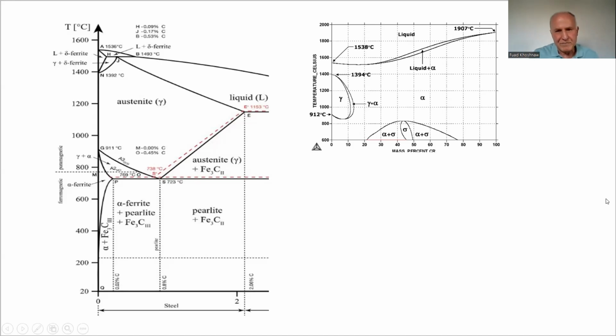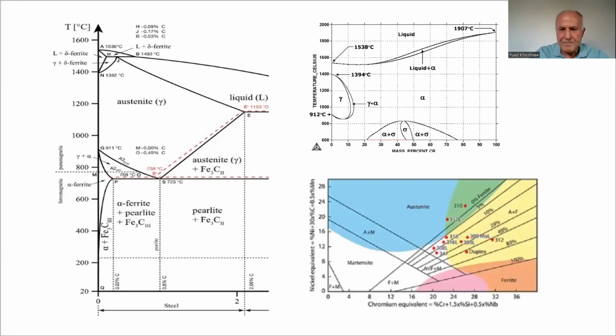And if we add both of them, chromium and nickel, there is a diagram called the Schaeffler diagram that uses chromium equivalent and nickel equivalent. So that's equivalent, including chromium, silicon, and niobium. But for nickel, it is nickel, carbon, and manganese. So they don't have similar effect, they have difference. For example, let's say this one, I can read that better: 1 chromium is equivalent to 1.5 silicon, and it is equivalent to 0.5 niobium. So if you add 0.5 niobium, it acts similar to 1 chromium. So the weight of action can add.